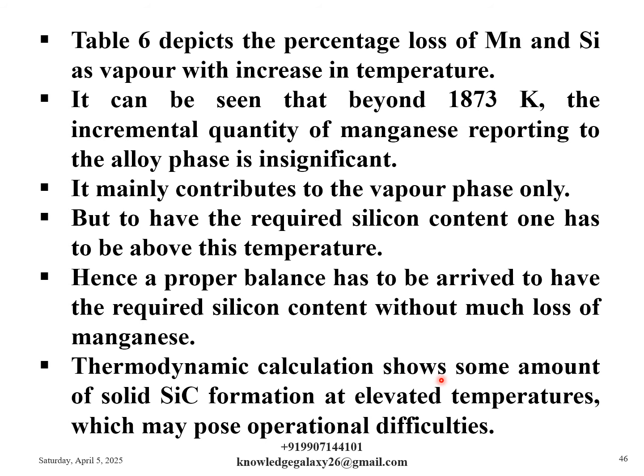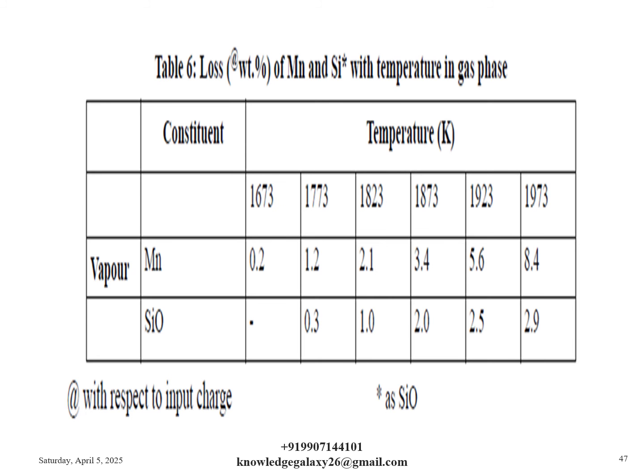Thermodynamic calculations show some amount of solid silicon carbide formation at elevated temperatures, which may pose operational difficulties. So this is the table 6, which shows the loss in weight percentage of manganese and silicon with temperature in gas phase. Okay, so far so good.